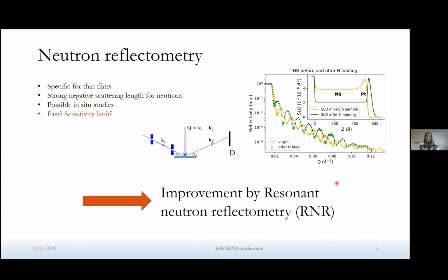Since NR has been very well introduced yesterday and today on several occasions, I will not spend time explaining details, but I'll just focus on its role with hydrogen. Because we are using neutrons as a probe, of course, due to the strongly negative scattering length of hydrogen, we are very sensitive to this atom. And in general, hydrogen in a film will decrease its scattering length density, as you can see here, before and after hydrogen absorption. And also, because neutrons interact very weakly with matter, it is possible to perform in situ measurements in hydrogen atmosphere.